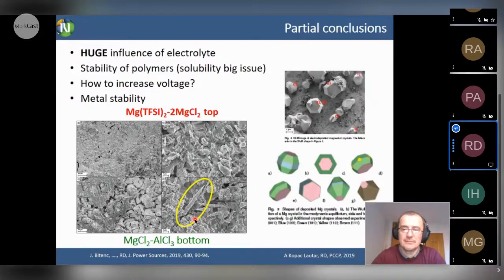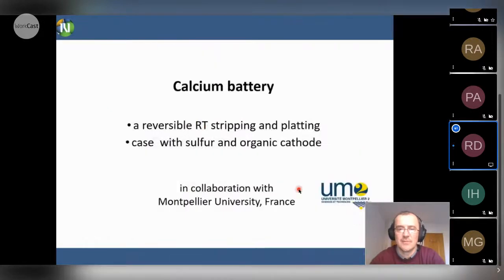And how to explain this? We performed a study of interfaces which are stable and which are not stable, and it was reported that 001, this pinky interface, is a stable interface. But of course, when you go to faster kinetics, when you want to work a little bit faster, other interfaces also become active because of polarization, because the potential difference between those two interfaces is not so huge, and then other interfaces don't allow homogeneous deposition, but they prefer dendrite type of deposition. So that shows another point which we need to be really careful about when we are designing a magnesium battery.